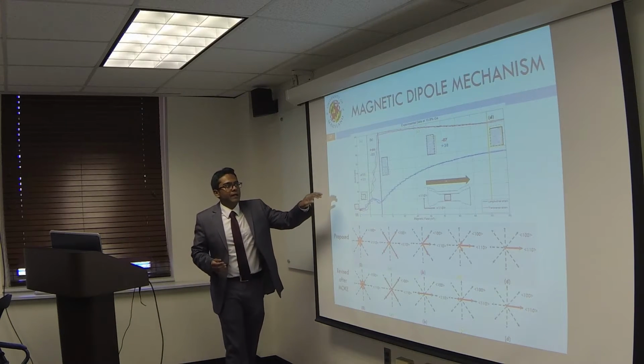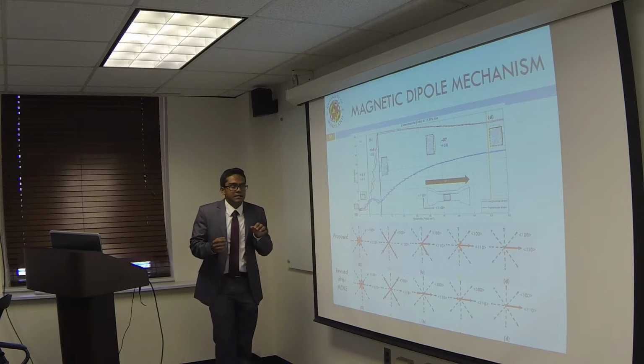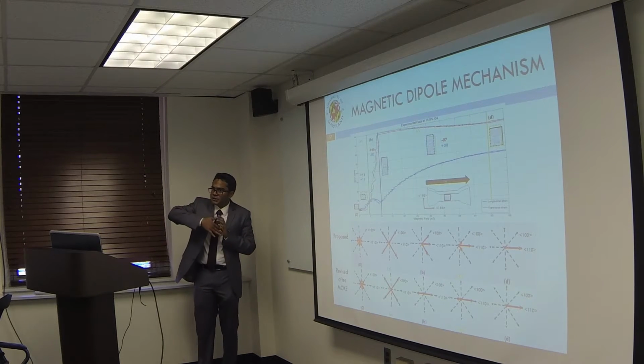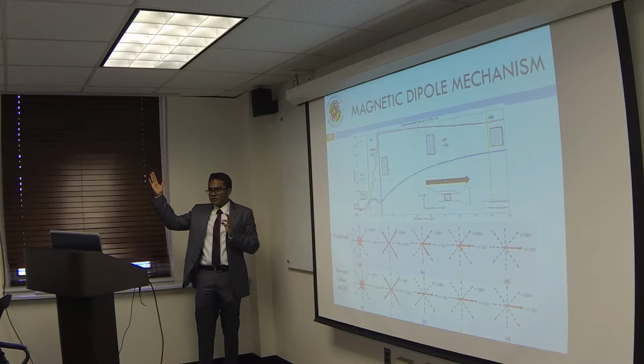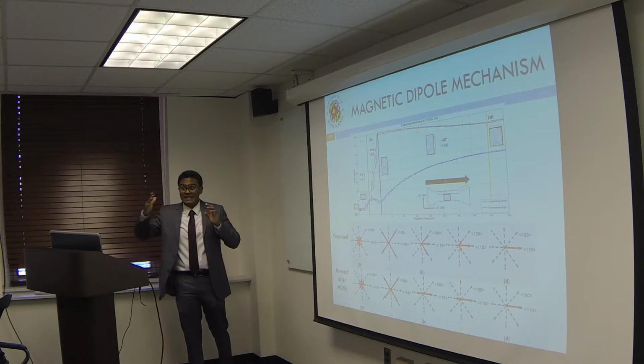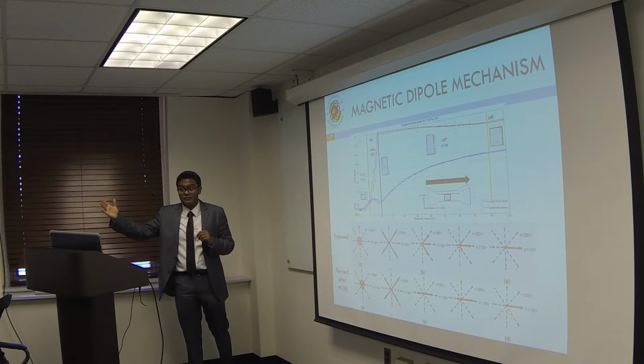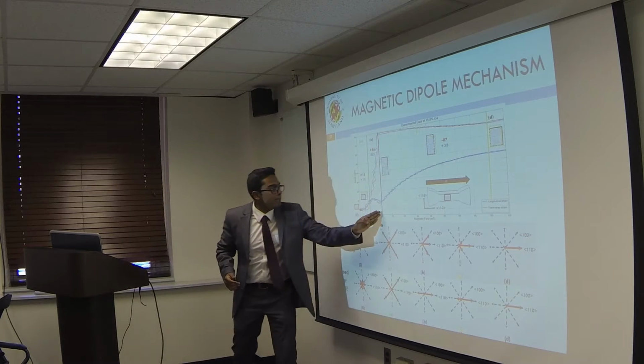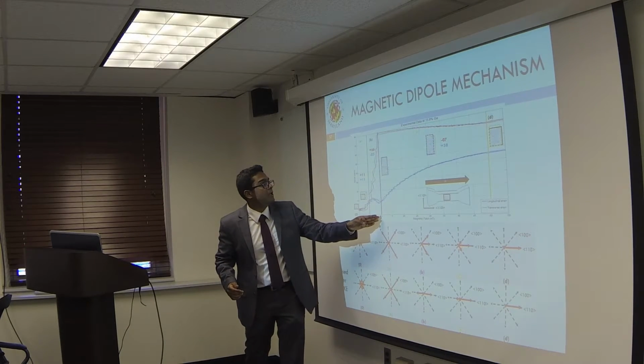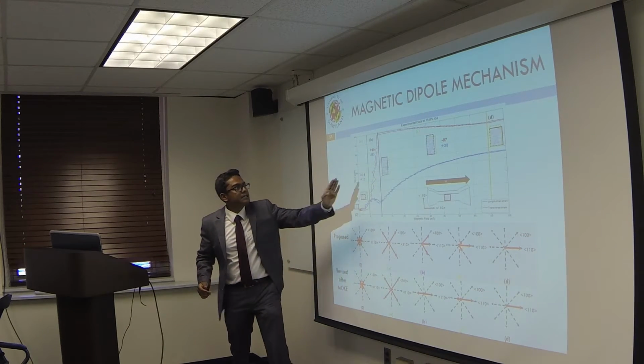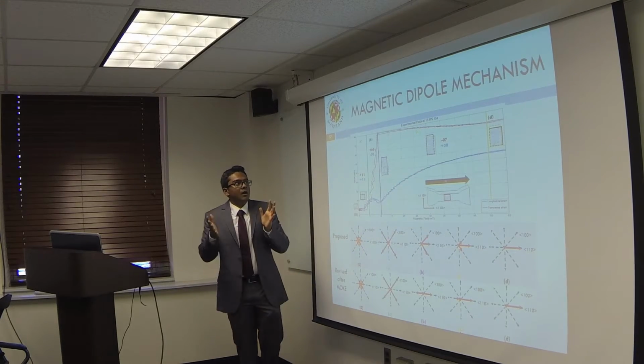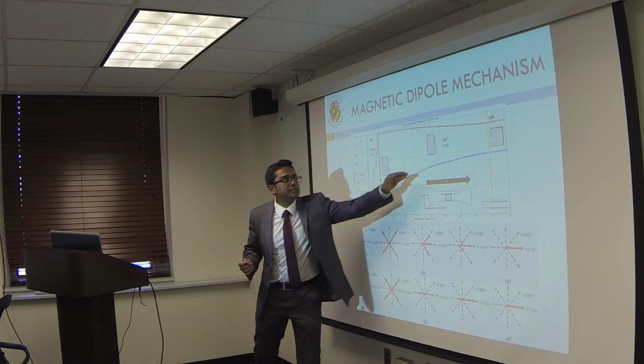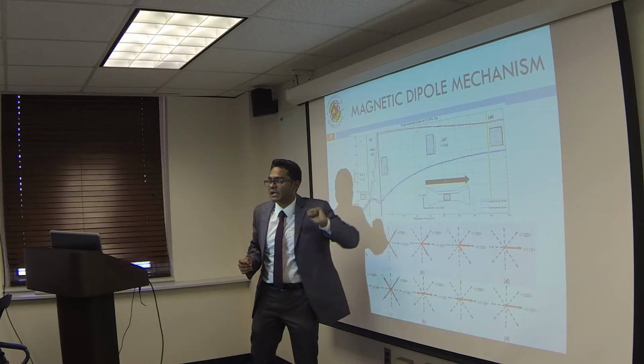So the way in which we need to understand what's going on in Galfenol is, at small magnetic fields, there's a rotation of the dipoles to orient themselves along the applied magnetic fields, and this is the reason for the large increase in the transverse strain. And past 10 millitesla, past region B, it seems to behave like a regular material where there's an increase in the longitudinal strain and a decrease in the lateral strain.